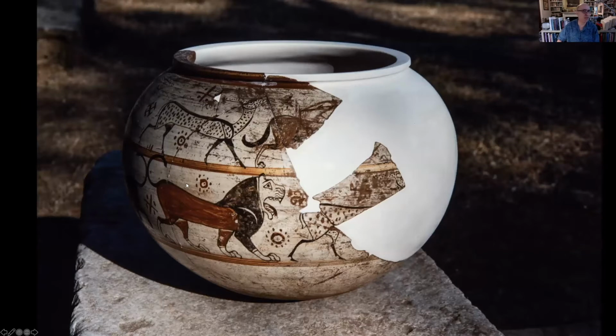This is the Lebes before inpainting, but after reconstruction and filling. The plaster has been leveled, smoothed by sanding, and it's been consolidated with a dilute form of the same B72 acrylic resin. This seals and stabilizes the plaster and provides a suitable base for the paint.